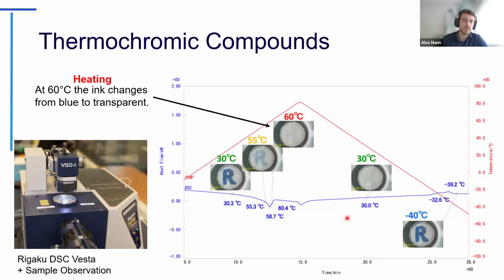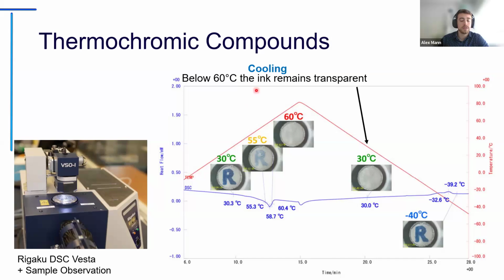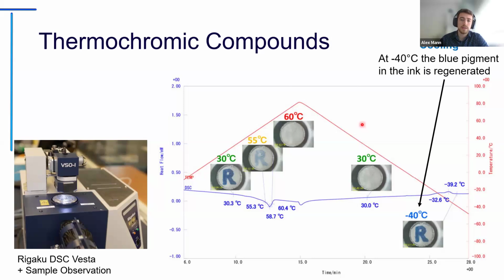So as we can see here, looking at our data, the thermochromic compound goes through a color change at around 60 degrees Celsius. So the ink changes from blue to transparent. And then on the cool down, we notice that as we go through 60, the ink remains transparent. Then lastly, once we cool it down to -40, the blue pigment in the ink is regenerated. So what we see here is that this thermochromic compound is reversible. However, the regeneration temperature is way below the initial color change.